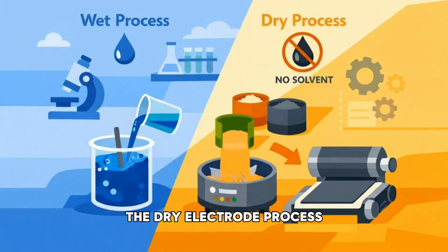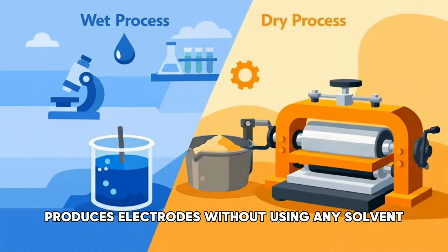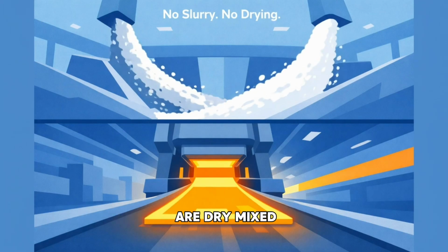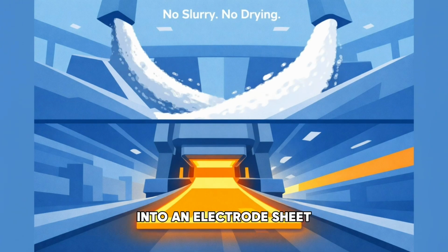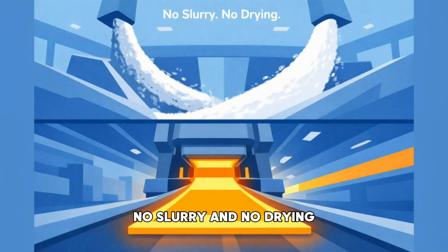In theory, it's very simple. The dry electrode process produces electrodes without using any solvent. Powdered active material and binder are dry mixed and then directly compressed into an electrode sheet. In other words, there is no slurry and no drying step at all.